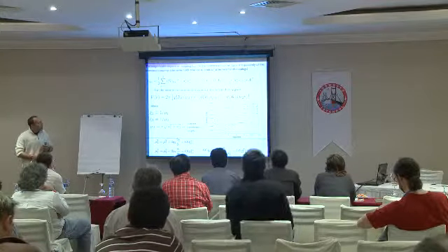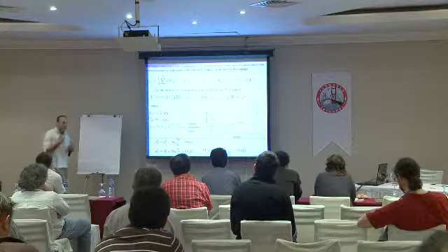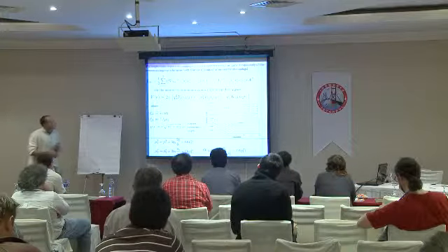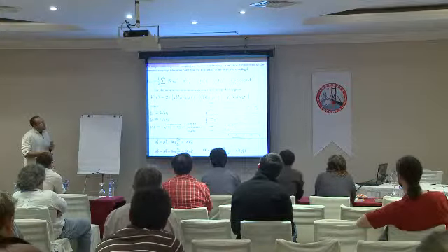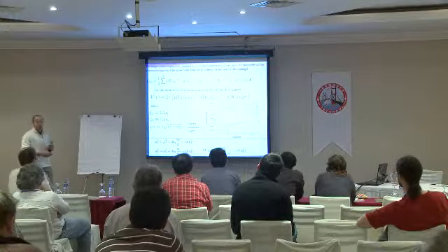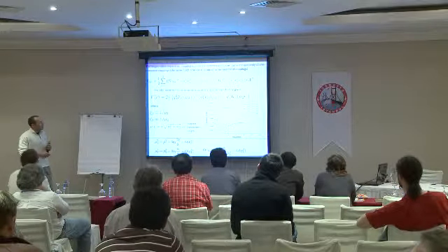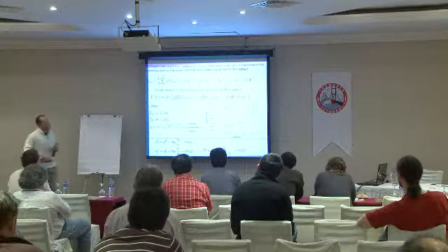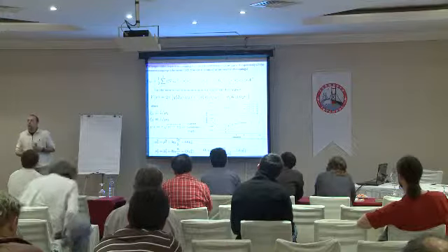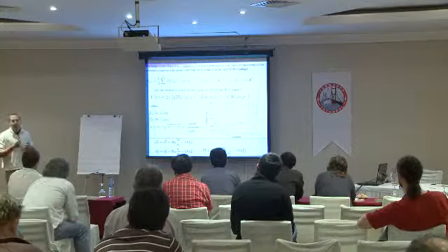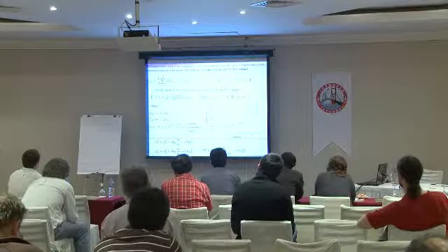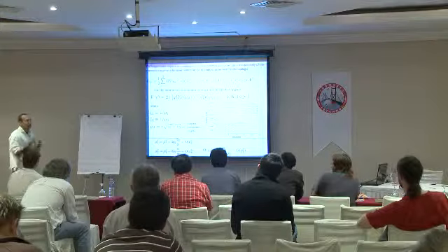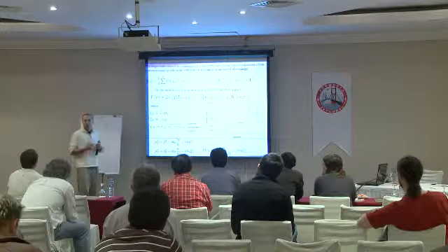Then, going to a representation in linear combinations of the original fields, we can always decouple the linearized theory into two decoupled equations. And it will give exactly the same kind of intervortex interactions as in the U1 cross U1 theory, except that now our coherence lengths cannot be attributed directly to gap 1 and gap 2, but they can be attributed to linear combinations.